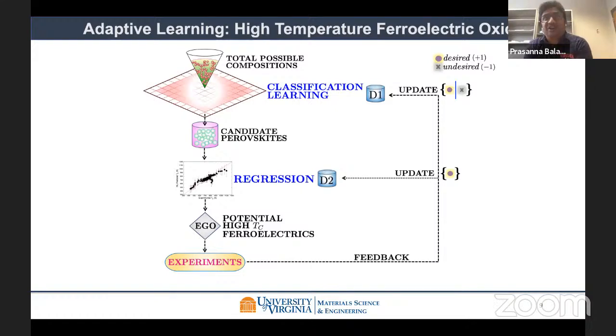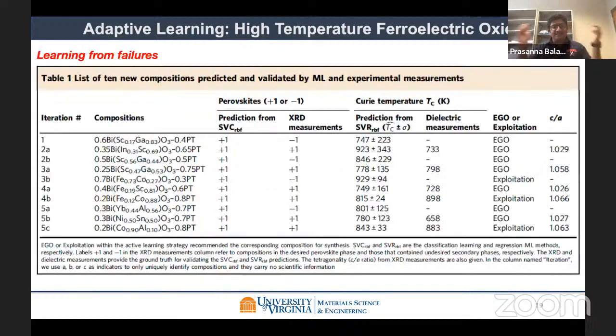If the X-ray diffraction did not result in the structure that we desired, we still update the classification learning model, but we do not measure, for example, the Curie temperature, because the material is not a perovskite crystal structure anymore. I hope this logic is clear, but I'm happy to explain it later in the Q&A session. We applied this loop and performed five sequential iterations, running 10 new experiments, and I'm going to walk you through them.